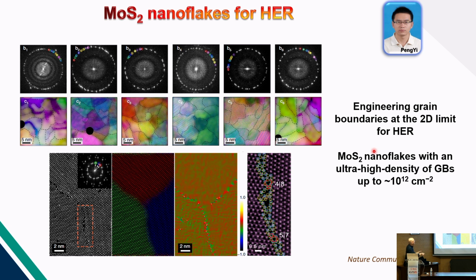So in this case, it is a reaction of hydrogen evolution. So what we want is to use this material. This is a publication from 2020, so it's a long time ago. But the idea is you can use this material, molybdenum disulfide, in order to do a good hydrogen evolution reaction, but then you realize that this material is not working at all. So the idea of molybdenum disulfide is that you have a sandwich. You have sulfur, molybdenum, and sulfur. So the basal plane of molybdenum disulfide is quite inert.